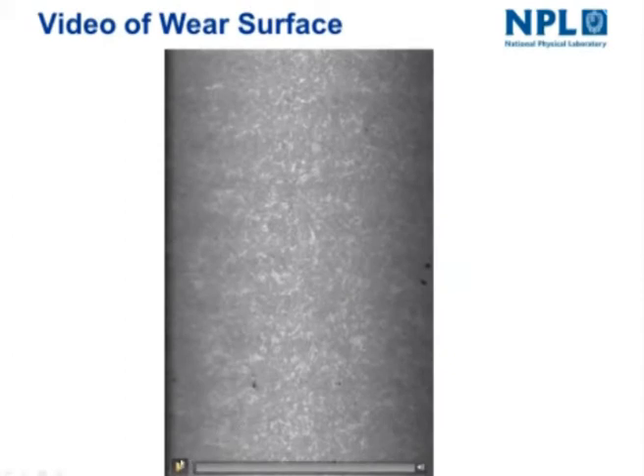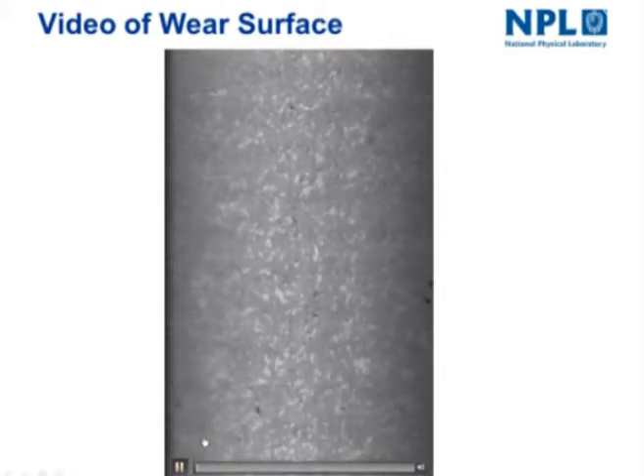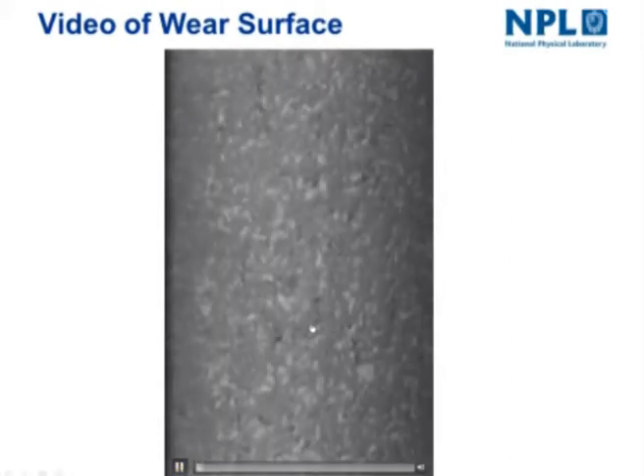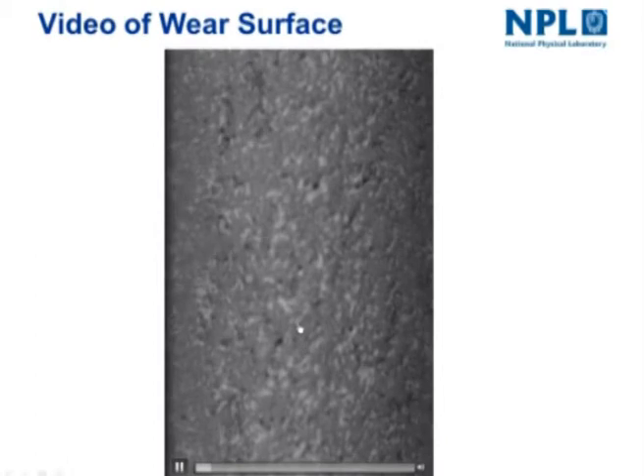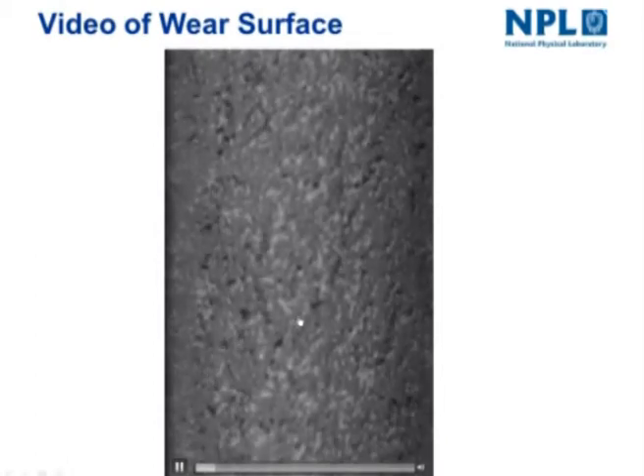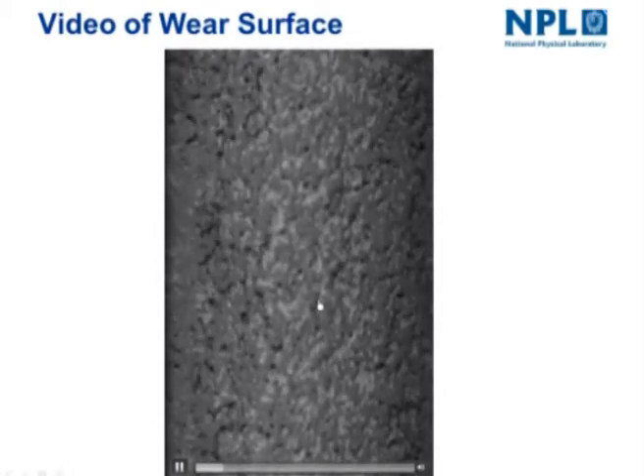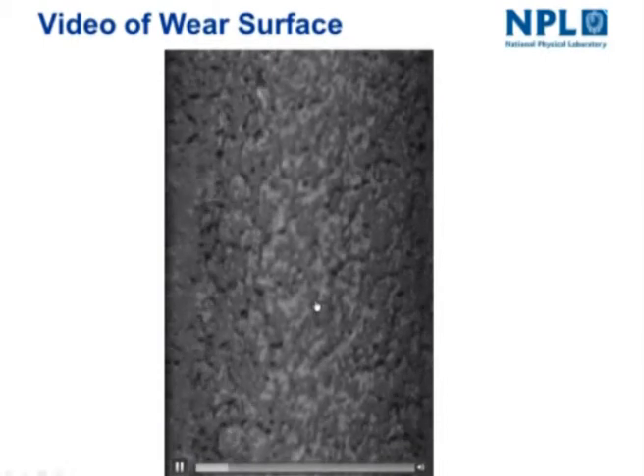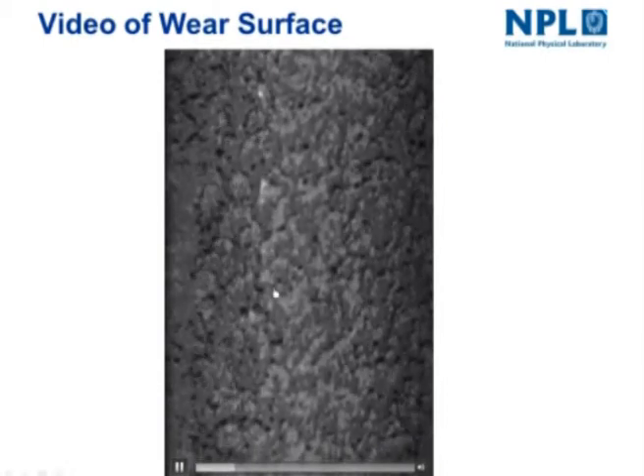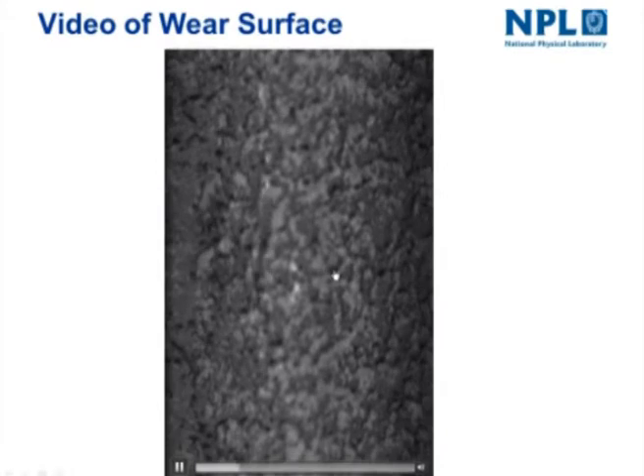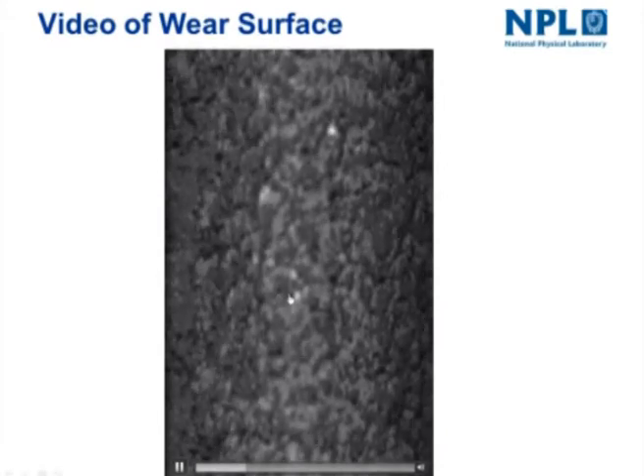And here we have a video produced from this line scan camera. I'll bring the mouse back so I can run this. And so this is the surface of the alumina, and it goes in and out of focus. We need to refine the technology, but you can see that pits start appearing in the surface as the surface is damaged. Then these little black specks start appearing, which are adherent to the surface.